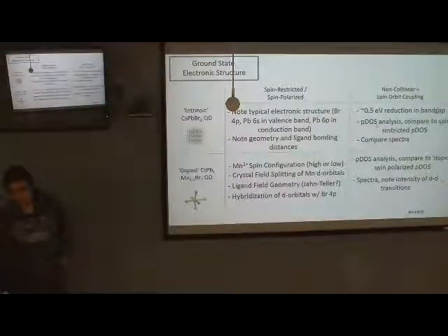You do the spin orbit coupling. Spin orbit coupling. And then it reduced the band gap by about 0.5 eV, which has been reported by other people. And then I was going to do a PDOS analysis because of spin orbit coupling.